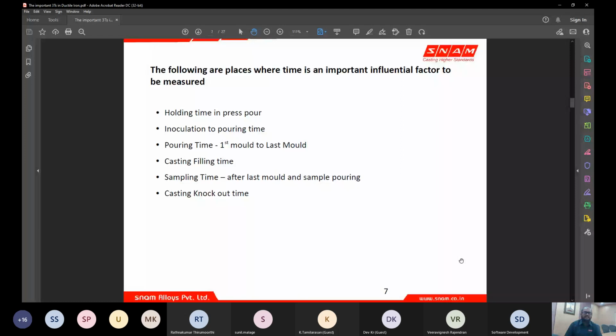Let's say pouring time is 8 minutes 30 seconds, rather than comparing with foundry A, which is pouring in 10 minutes with a different setup. So time plays a major role, because as we saw previously, all the chemical reactions are time dependent. And casting filling time talks about the mold filling time. In case there is an auto pour system, which is generally controlled by pneumatic or some mechanical operations, the filling time of a mold is going to be constant. If the filling time of the mold is averagely constant, you're going to get uniform cooling time and uniform properties throughout the castings.